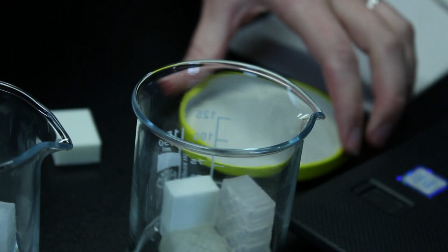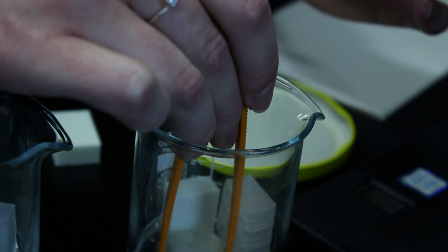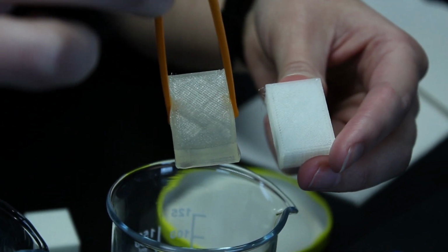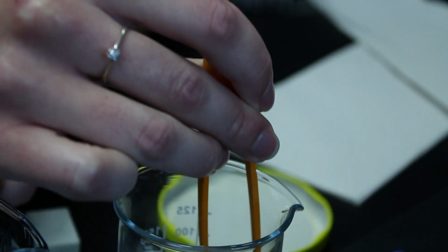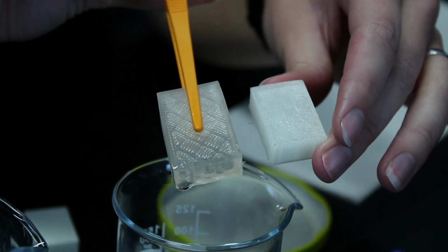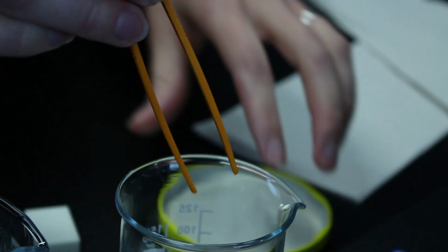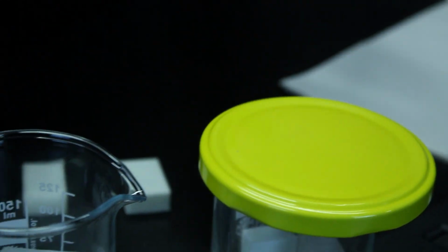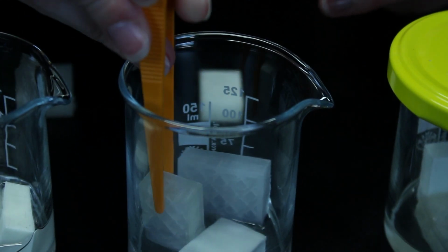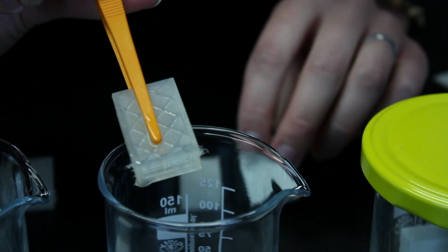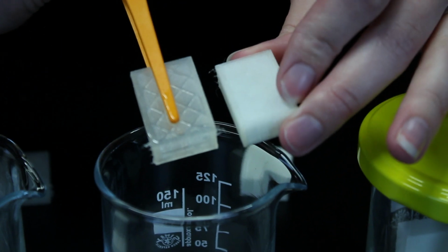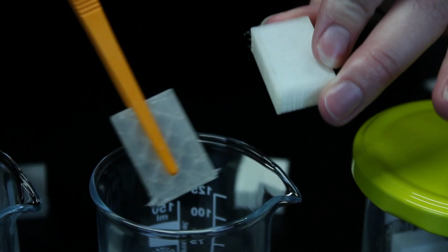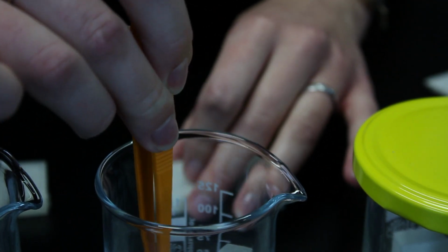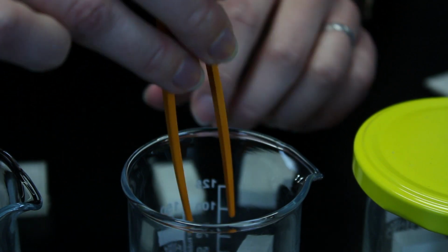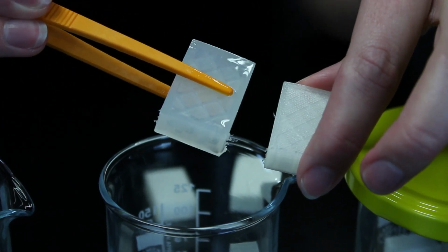In case of formic acid, TPE has good resistance, TPU has swelled already after 1 hour, and PBA has a very hard swell after 4 days. In case of isopropyl alcohol, we can see that TPU has swelled a little bit and became more transparent, and PBA has swelled to a nice swelling.